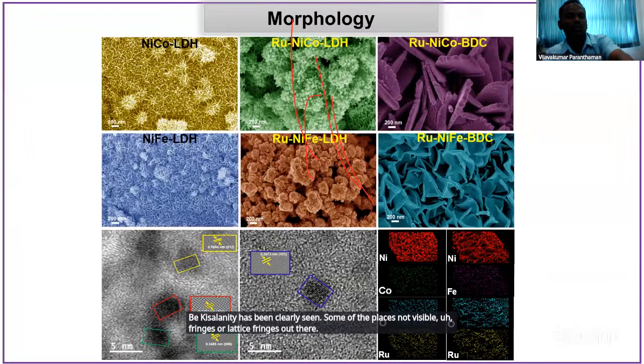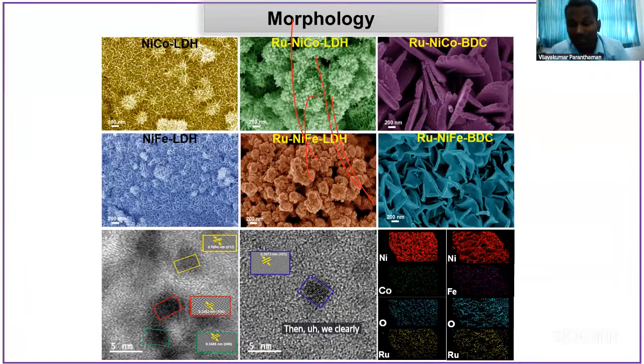See the HRTEM images, there is amorphous character. It is not a good crystalline material. Weak crystallinity has been clearly seen. In some places lattice fringes are not visible and in some places they are there. So we concluded this is a mixed amorphous and crystalline behavior. Then we concluded that all the elements, like Ni, Co, and oxygen, are uniformly distributed over the material.